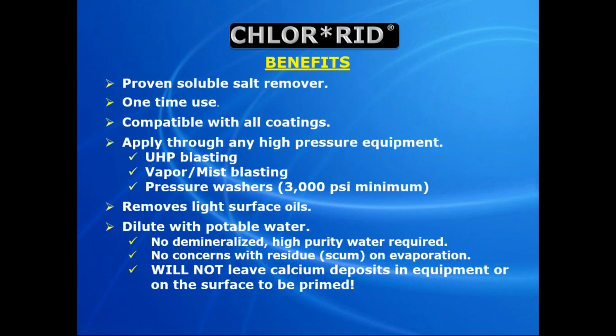And it dilutes with potable water. We don't need high purity water or demin water. There's no concern of scum, residue, on evaporation. Some of you with vapor blast equipment have seen in the past where the machine starts clogging up after using inhibitors, and you need to bring it in for repairs, and you need to get all the calcium buildup that's inside those machines and clean it up. Well, with our products, there's no worry about that. We don't have that type of issue. We will not leave scum on the surface.